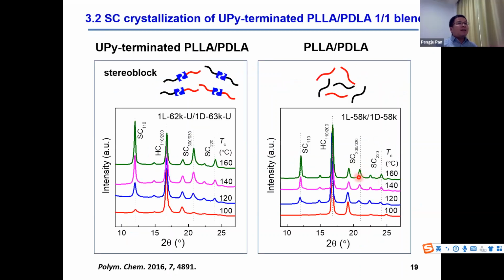We then mix the UPy terminated PLA and PDLA and crystallize them at different temperatures to study the effect of terminal hydrogen bonding interaction on crystallization structure. We compare the XRD pattern with a non-functionalized PLA and PDLA blend. By comparing the XRD pattern of the samples crystallized at the same temperature, we can see the content of stereocomplex increases after the introduction of UPy unit. But this effect is not so significant in the case of polymer containing one UPy group because 2 PLA and PDLA chains can also link together by the UPy hydrogen bonding interaction.